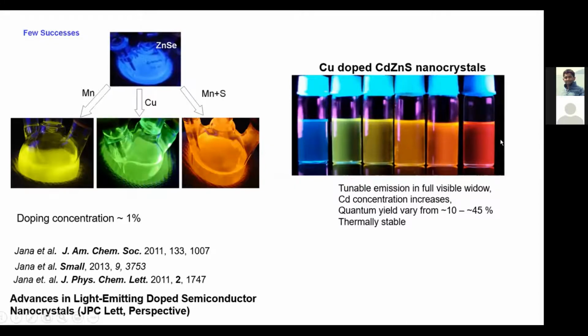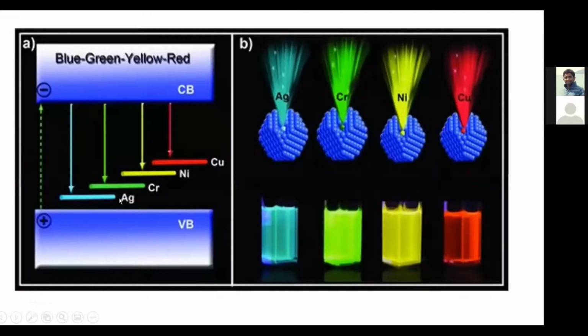And another thing, if you put the copper in other nanocrystals like cadmium zinc sulfide, you will have a full visible window. And here you can see, because it's a little bit low toxic, because cadmium concentration decreases, you will have not fully cadmium sulfide, and also the quantum yield will be high. And an interesting thing is that without coating, without core-shell structure, it is very thermally stable in the solution. And you can also dope with other transition metal ions, chromium, nickel, copper, and silver also.